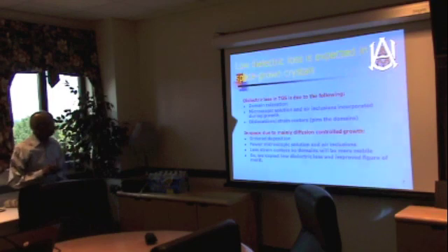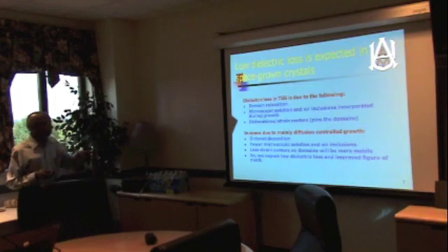The next question was why we chose TGS. The dielectric loss is expected to be lower in the space-grown crystals, which is what we expected. The dielectric loss in crystals is because of domain relaxation, because TGS crystals have electrical dipoles, plus and minus, and they are all randomly oriented. So if they are all arranged in a proper fashion, then the crystal will give better quality. So the domain relaxation is due to that, and the microscopic solution and air inclusions during crystal growth.